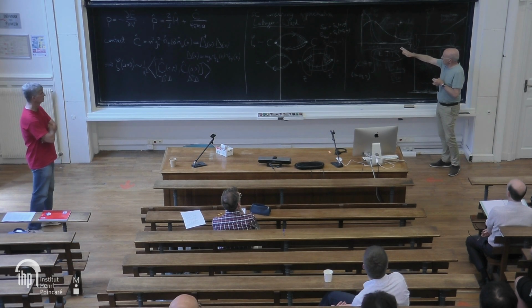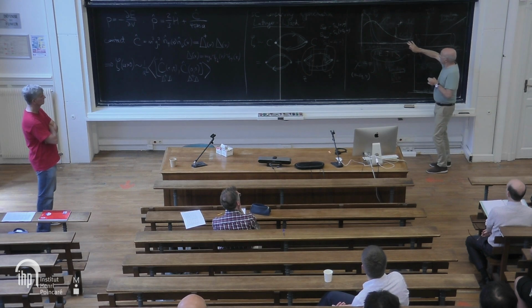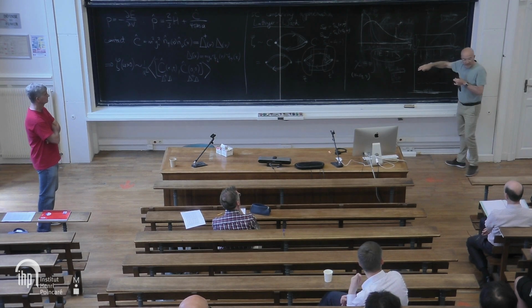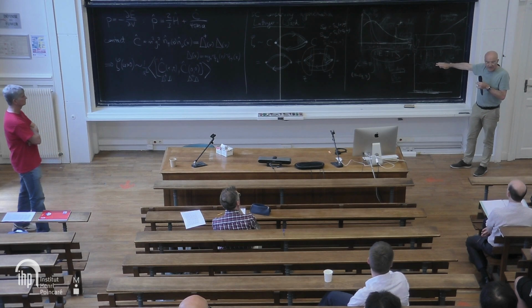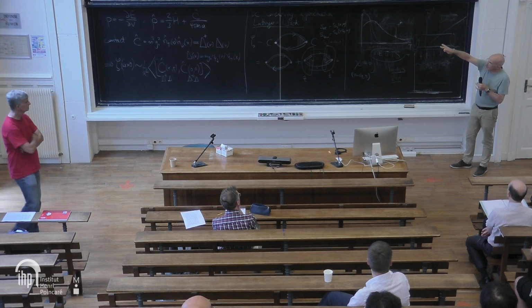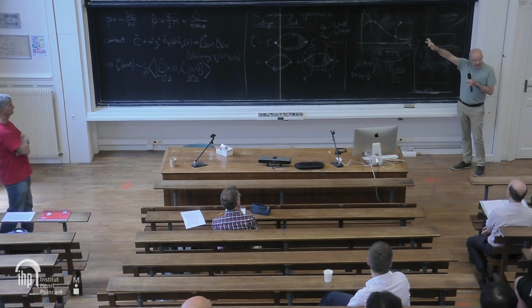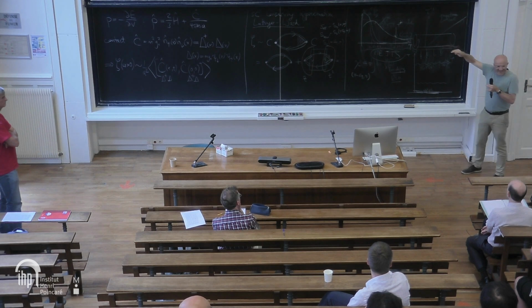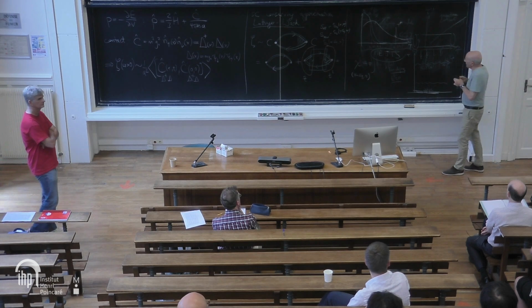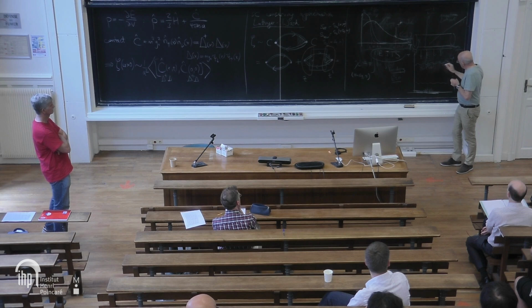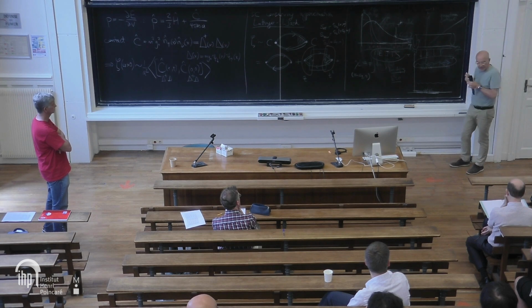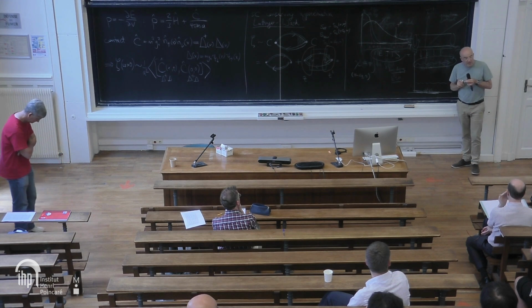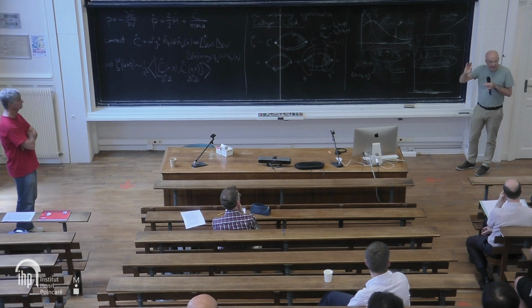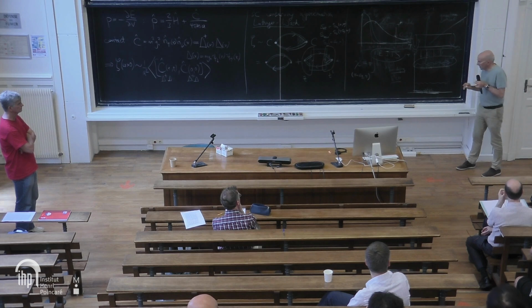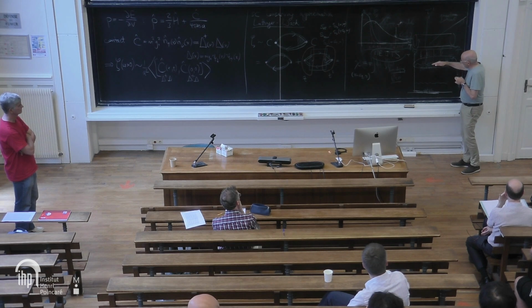And just to finish the story, this picture we've done recently with Riccardo Rossi and Fedor Simkovic and Michel Ferrero, a study using the third technique I was describing, namely seeded diagrammatic Monte Carlo, which Felix likes. And what we find is that indeed this scale is reachable with diagrammatic Monte Carlo. This is an old paper, 6 or 7 years old, that we did with Wei Wu and coworkers. But now we can also do this at lower and lower temperature.